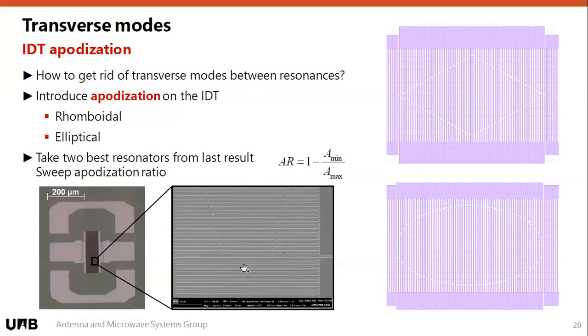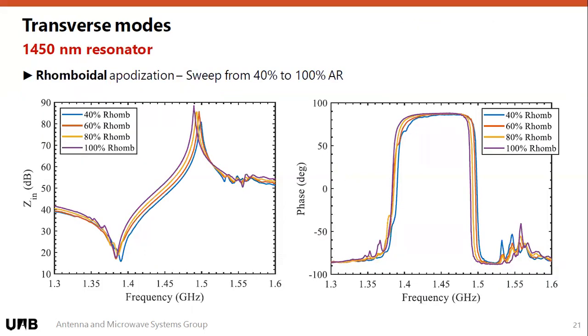Here we just have an SEM image of one of our apodized resonators. So you can see that we had to cut a little bit the finger at this position so that the active area of the resonator actually defines this rhomboidal shape. Okay, so we'll go through both the rhomboidal and elliptical, but we take the 1450 nanometer resonator, and we have a sweep from 40% to 100% apodization ratio.